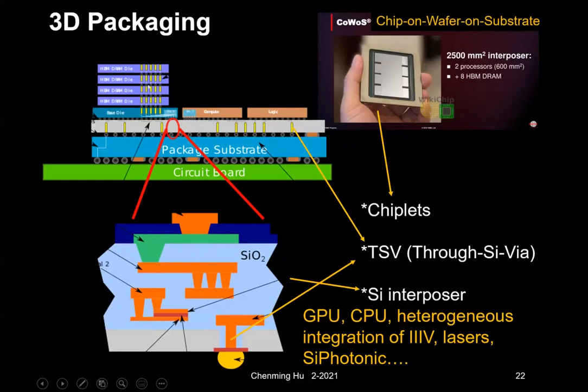And not only that, there's something called through silicon via. Then the silicon 12-inch wafer can have holes through the thickness of the wafer, and the holes are filled with copper that allows this package to be further connected with other such packages if necessary. So the package is also going 3-dimensional. And by doing that, we could even consider these wafers, processors, could be stacked together. And not to mention, last slide, I said each of these processors can have 2 layers of circuits or even 5-6 layers of circuits. So that's the direction.